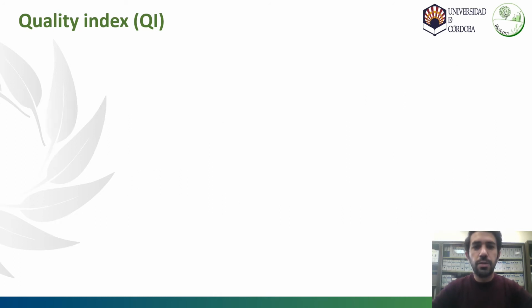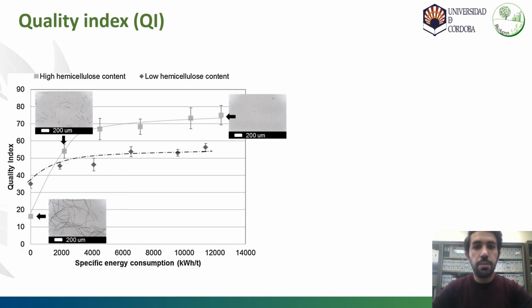In order to study the suitability of this index for the analysis of different fibers, several tests were carried out. In this one, we see how pulps with different hemicellulose content were subjected to a mechanical fibrillation process, observing that when the energy consumption increased, the quality index increased due to the greater nanofibrillation, but it reached a plateau phase where the nanofibrillation reached its limit for this type of fibers. We also observed that fibers with higher hemicellulose content result in a greater increase and a higher quality index. This is due to the inhibition of coalescence of the cellulose nanofibers in aqueous medium when they are surrounded by hemicellulose, maintaining the nanometric size achieved in the fibrillation treatment and avoiding their agglomeration.